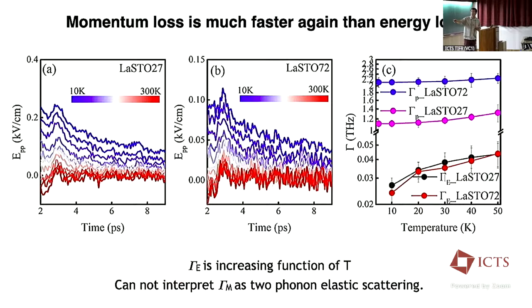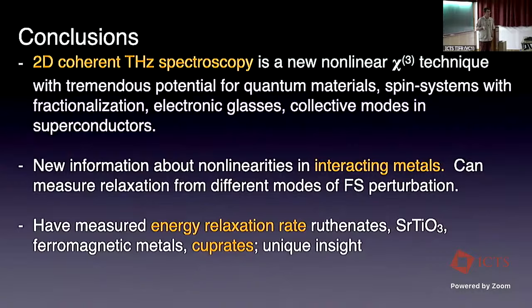rate is an increasing function of temperature, and this scattering, which is T squared, is much, much larger than that. So you can't, if you will, postulate some kind of weird acoustic phonons that are giving you some funny power law that's leading to T squared resistivity. So that's something that we rule out as well. And I'll just finish with that, and I'm happy to take questions.